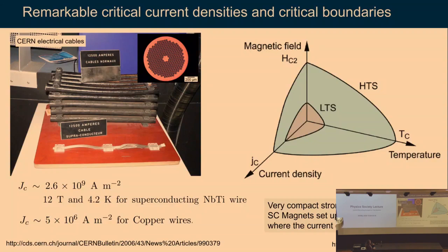And here I want to show you that a superconductor is characterized by its critical parameters, so it's the critical temperature. Unfortunately, many of them only superconduct at low temperatures. By its critical current density, so above a certain value, you will destroy the superconducting state. And obviously, the critical magnetic field. So above a certain value of a magnetic field, you will destroy the superconducting state.